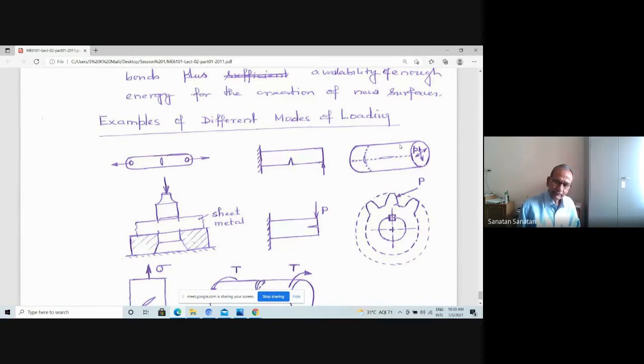So the crack along the longitudinal direction is being opened up by hoop stress, and therefore that is a mode 1 crack. And if you think of the other crack, in the circumferential direction, in a closed cylindrical vessel with internal pressure, the pressure acting at the two ends tries to separate the crack on the crack plane, and therefore that is again a mode 1 crack. So a longitudinal crack is subjected to mode 1 loading because of the hoop stress, and a circumferential crack is loaded in mode 1 because of the axial stress. So please note that.